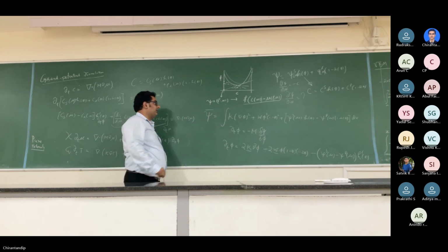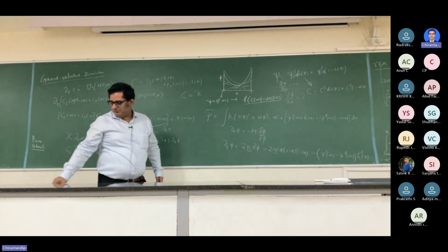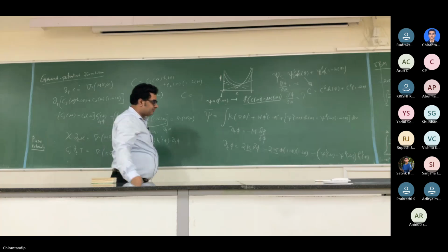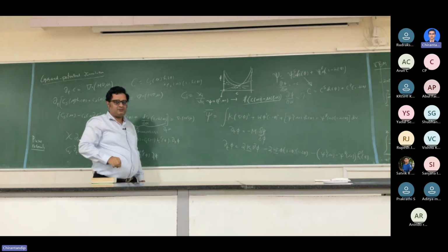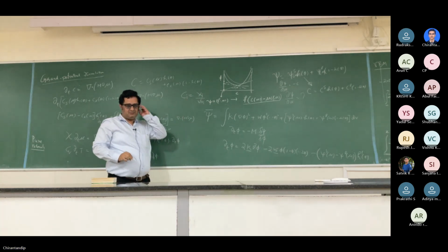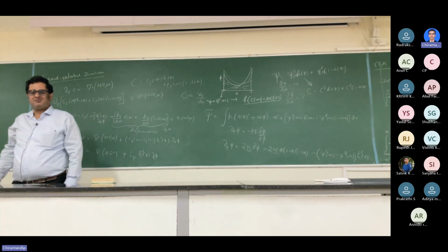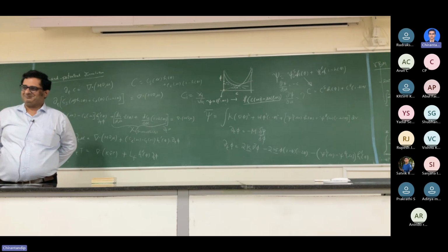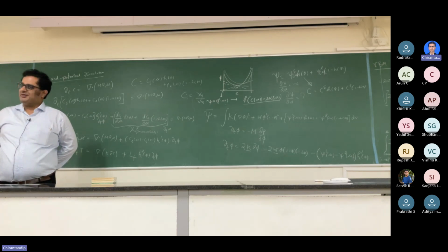So, for the case where C is equal to the mole fraction divided by the molar volume, this fundamental relation will hold always. And in all our models, even the KKS model and even this one, the inherent assumption is that the molar volumes of the components are actually equal. That's okay. Locally, we have to. It is all equal in the KKS model also and here as well.